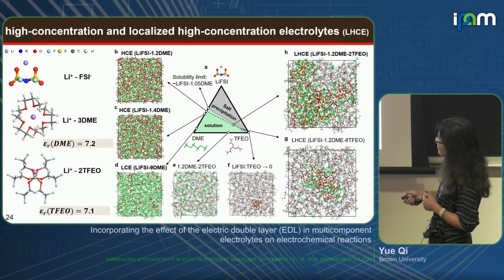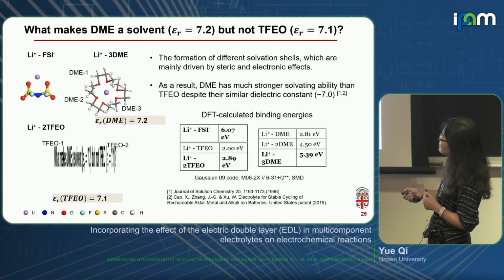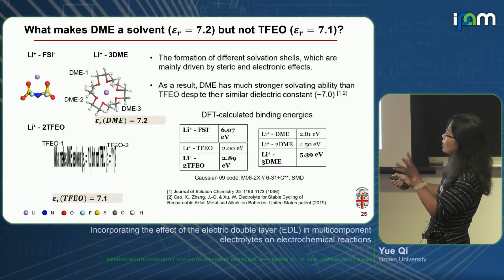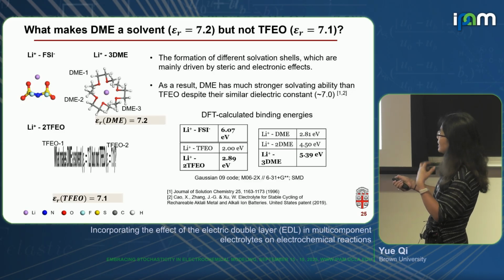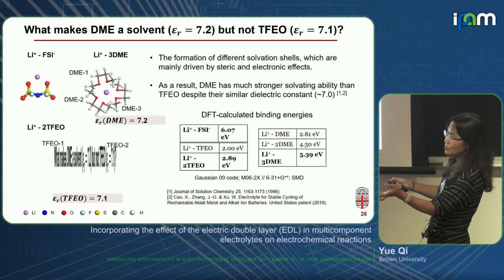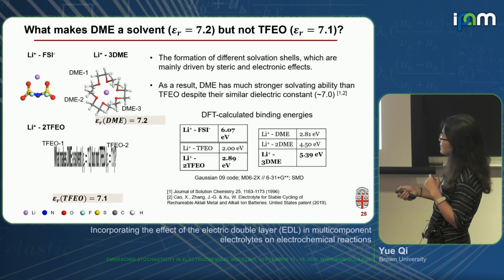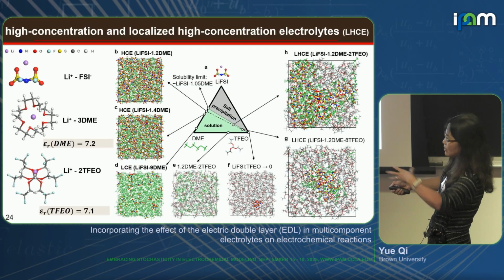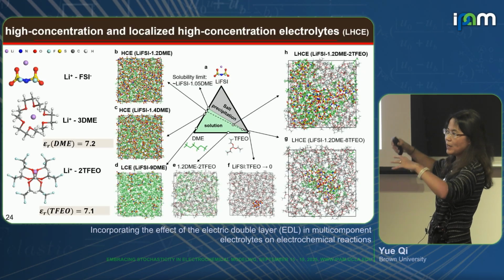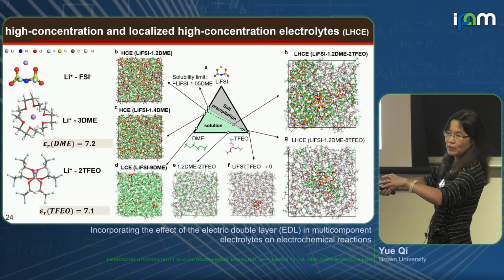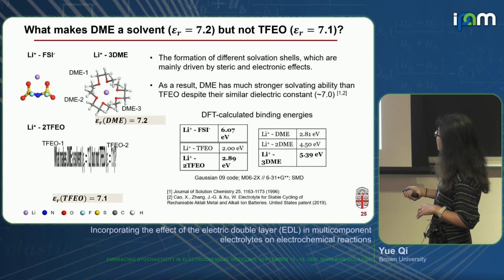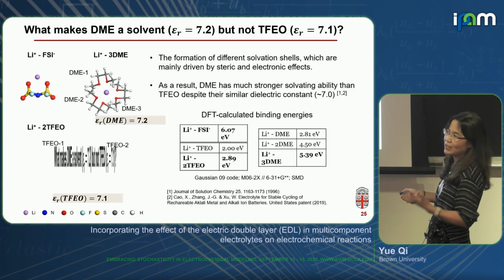Okay, so that's supposed to be this picture. It turns out that we can pack a solvation shell, 1, 2, 3 DME around the lithium, and then we can solvate it. We can take it out from the binding with the ion. But with a TFEO, if you see this molecule, they are really big, right? We packed 1, we packed 2, we could not pack the third one, right? If you see the solvation structures, the third one can't go.